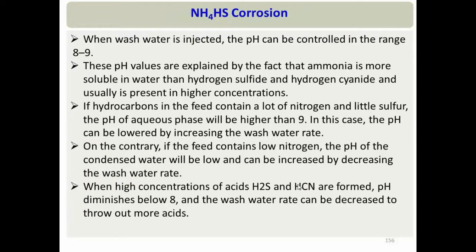Now based on that discussion, what we understand is that the water wash in the FCC overhead system needs its pH controlled very strictly. If your pH goes below 8, there is a problem of ammonium polysulfide decomposition. And if your pH goes above 9, then, as we have already discussed, the concentration of ammonium polysulfide will be high, and the rate of corrosion will also be high.